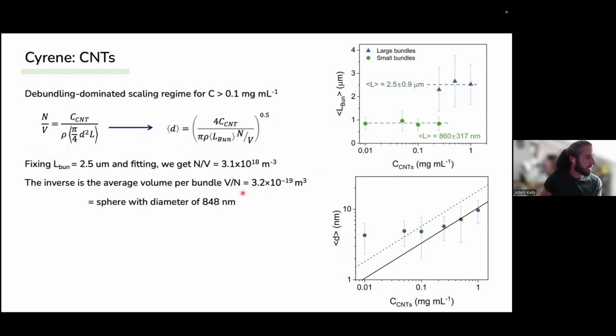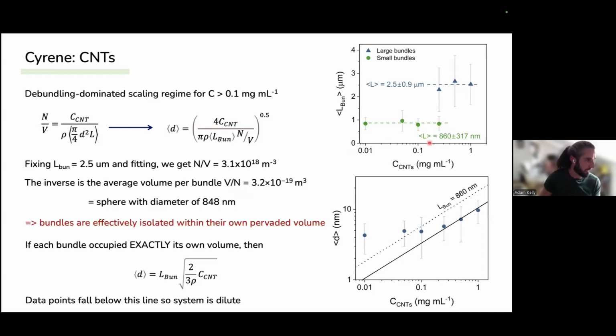It turns out this is the volume of a sphere whose diameter is 848 nanometers. So that's pretty close to the length of the small bundles. What this means is that the small bundles are effectively isolated within their own pervaded volume. To analyze this a little bit further, if we assume that each bundle occupies exactly its own volume, then we put this sphere volume back into this value here, and this equation collapses down to this simplified equation here.